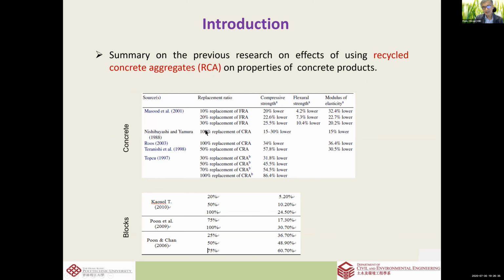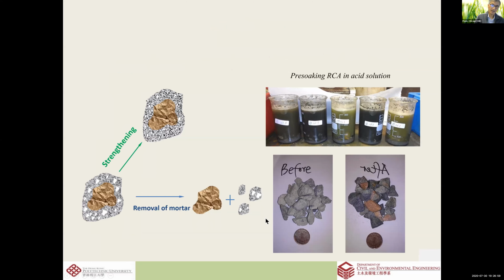Okay, so this is some of the results, though it's too small for you to see. But anyway, it summarizes that the use of recycled aggregate in new concrete, without any modification of the aggregate or the mix design, will lead to about 10 to 30% lower compressive strength, more than 30% lower modulus, and also very poor durability. So this is the culprit, the bad thing about recycled aggregate. This is the old natural aggregate, and this is a schematic of the old mortar surrounding the old natural aggregate. And this old mortar makes the recycled aggregate poor.